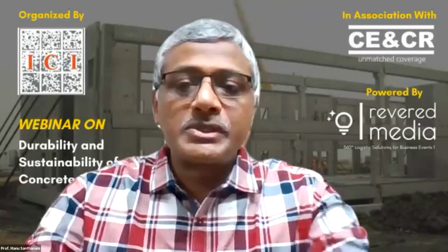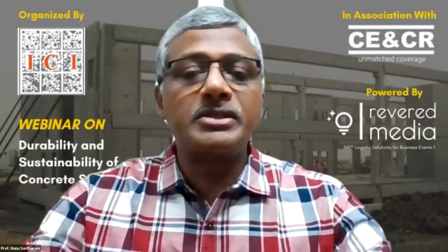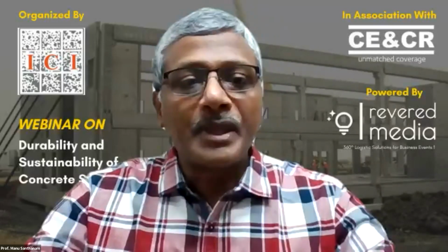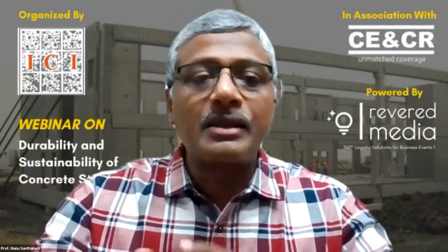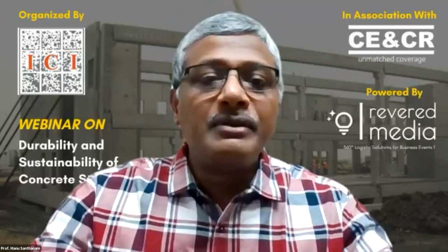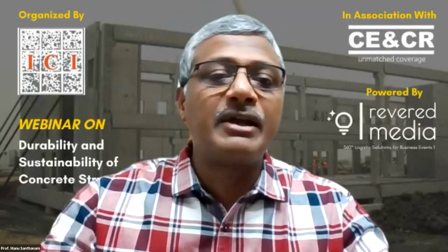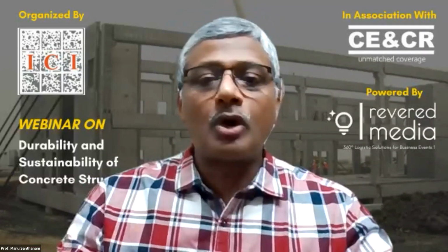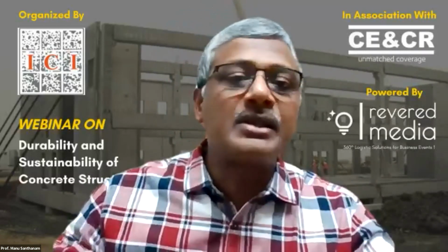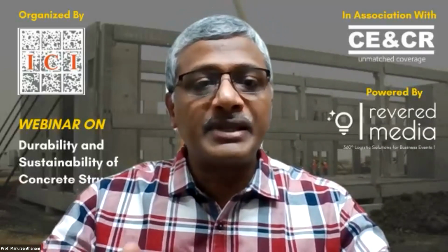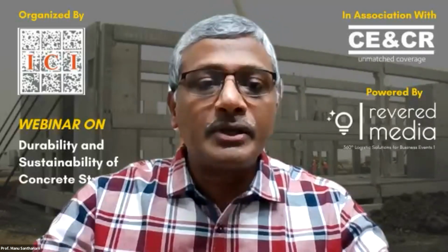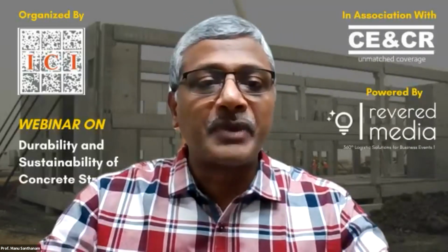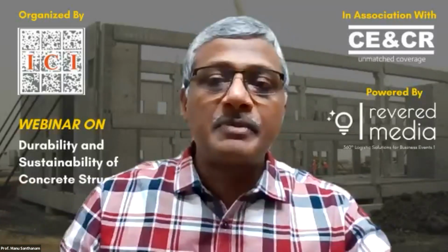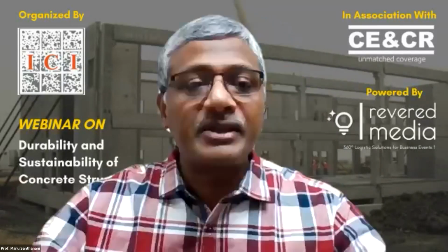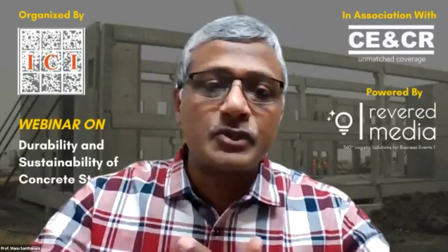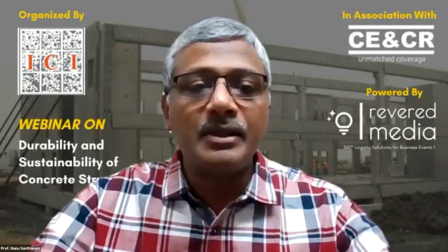Yeah, I agree mostly with that. Only problem is when we do these test methods that involve migration, which involve application of electrical potential, because in geopolymer concrete we use a lot of alkaline activators, and these alkalis sometimes are free in the pore solution. So even if the concrete is durable, sometimes the result shows that the RCPT value is very high. So you need to actually do a combination of tests, like a water absorption test or a gas permeation test in association with chloride-based tests. So tests based on migration may not be easily applied to geopolymer concretes, just like we have the issue with steel fiber concrete. Steel fiber concrete would be durable, but because of the steel fibers being present, giving continuity for the electrical conductance, migration-based tests need to be carefully applied. That's the only thing. Otherwise, as you were rightly saying, water-based tests should end up producing same durability in geopolymer concrete also.